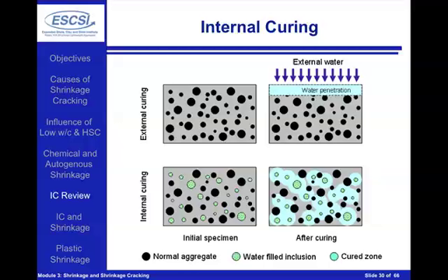And the goal here is really to do two things. One, it's to supply enough aggregate that you have enough water that it can essentially handle the demand that's going to be created by the hydrating cement. So you'll hear us talk about putting in enough water to compensate for the volume of the chemical shrinkage. What we want to do is provide enough water that can fill in all that vapor-filled space.